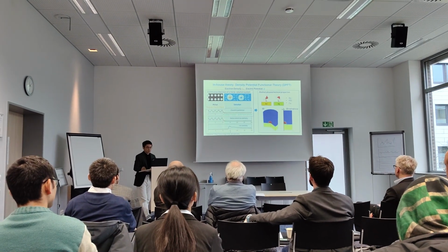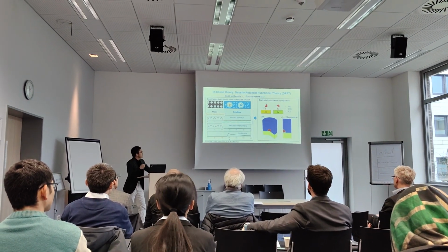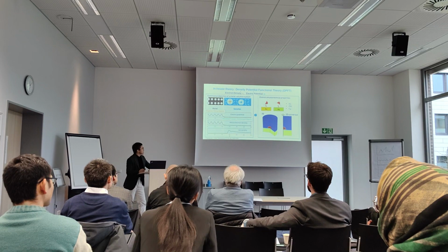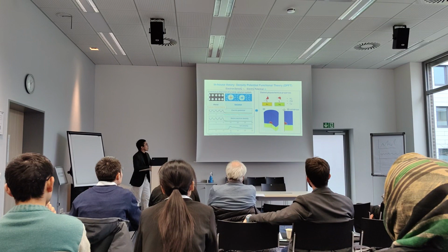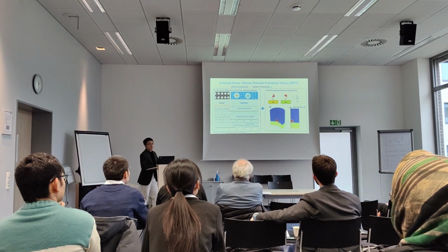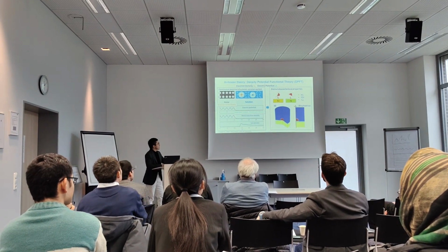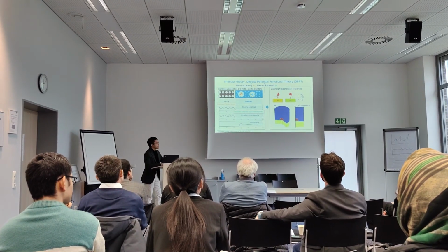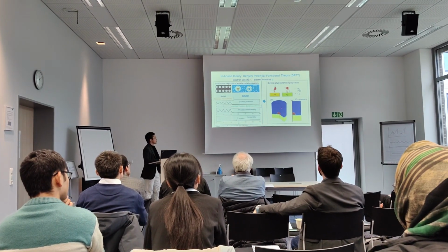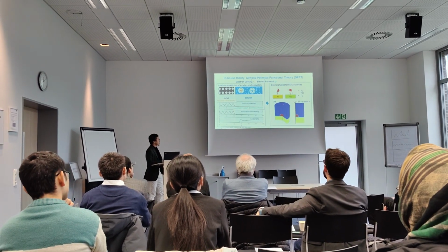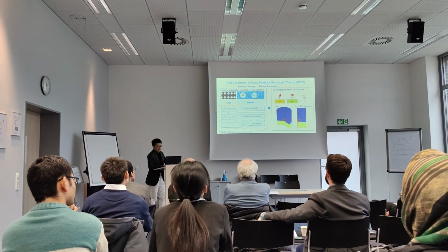In order to capture the distinct physicochemical properties of different metal materials, we made some methodological advancements to reproduce the experimentally measured work function, potential of zero charge, and differential double layer capacitance curve. This is a prerequisite of applying DPFT to the supported nanoparticle system. Later we made use of the axial symmetry to perform a dimension reduction from 3D to 2D, and we are ready to have the results.